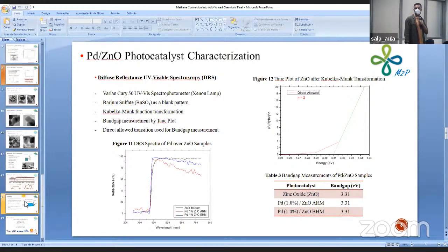We have then the diffuse reflectance UV-visible spectroscopy. The obtained spectra are at figure 11. Here we first can see that zinc oxide activation occurs around 380 nanometers of UV light. In the palladium-containing samples, we have some perturbation in the visible range. But this data was treated with the Kubelka-Munk function in order to relate the obtained reflectance to absorbance for powdery appearance